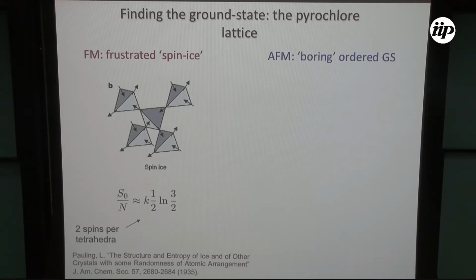So essentially your ground state entropy will be this: once you start putting them together, you have 2 spins per tetrahedron. And of those, you have 6 possible choices. I told you that for a single tetrahedron, you can have 6 choices. But there's only a 1/4 chance to match, so that this spin is pointing in the same direction, that it's the same spin in the next tetrahedron. So that gives you these 3/2. And for any of you who have looked at the water ice literature, you'll recognize this as Pauling's entropy.